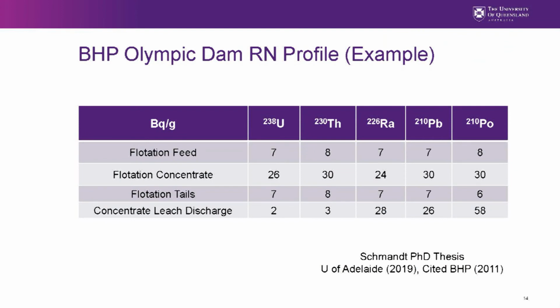Okay, so from an older BHP report, they've cited some of the radionuclide profiles in these streams related to the process I just described. So the flotation feed may have around 7 or 8 becquerels per gram, which is the unit of radioactivity. So 7 or 8 coming into flotation, but in the flotation concentrate, the radioactivity of the concentrate is actually significantly higher than the feed. Now we're up to 24 to 30 here. And the flotation tails look very similar to the flotation feed in this case.